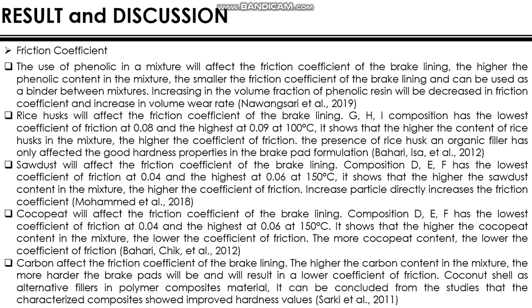Sawdust will affect the friction coefficient of the brake lining. Composition DEF has the lowest coefficient of friction at 0.04 and the highest at 0.06 at 150 degrees Celsius. It showed that the higher the sawdust content in the mixture, the higher the coefficient of friction. Cocopeat will affect the friction coefficient of the brake lining. Composition DEF has the lowest coefficient of friction at 0.04 and the highest at 0.06 at 150 degrees Celsius. It showed that the higher the cocopeat content in the mixture, the lower the coefficient of friction.